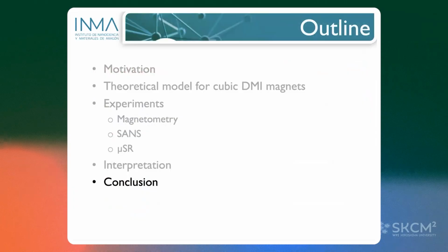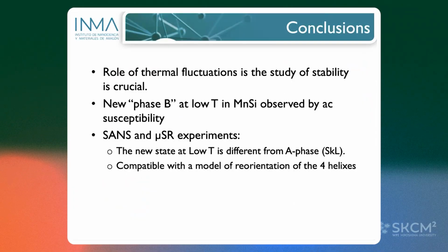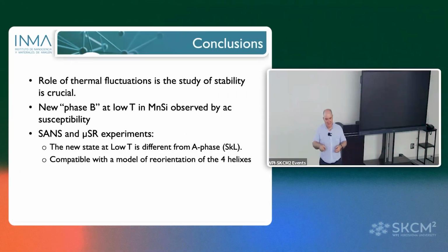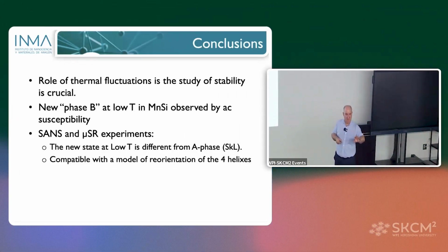Then, just to conclude, we analyzed the role of the thermal fluctuation. We anticipated the existence of the skyrmion lattices. This simple model, we know the limitations of the model. This model gave us the idea to explore the low magnetic field, low temperature part of the phase diagram. We went there and we found something. This something we know cannot be described by the model. We know the limitations of the model.